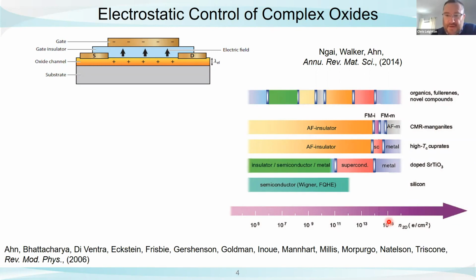Now, to put that in context, a standard SiO2 gate dielectric will break down at about 1 times 10 to the 13. So there's a 2 order of magnitude gap between what we can do with conventional dielectrics and what we need in order to be able to manipulate materials like manganites. So this is a problem.